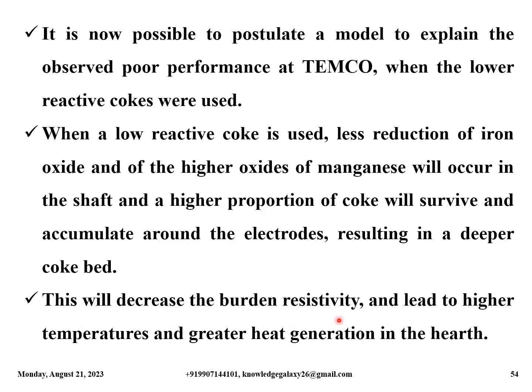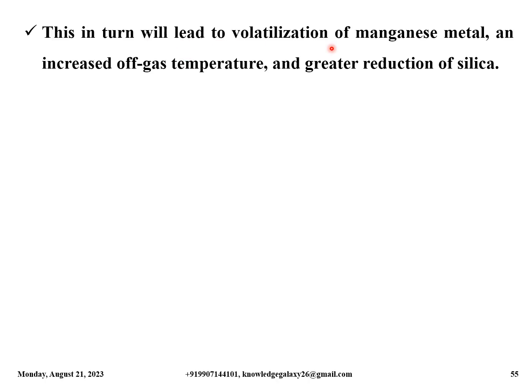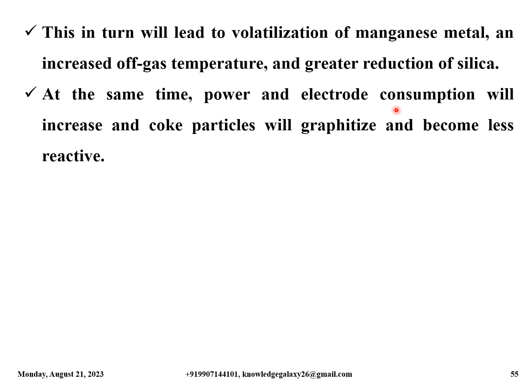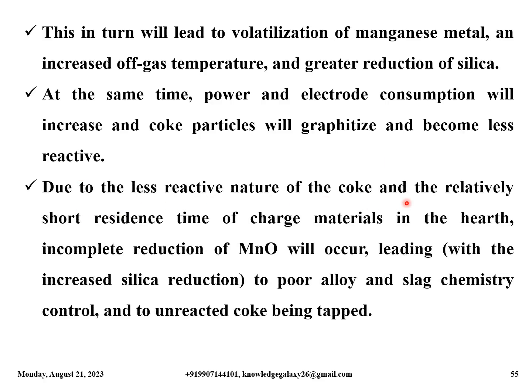This will decrease the burden resistivity and lead to higher temperatures and greater heat generation in the hearth. This in turn will lead to volatilization of manganese metal and increased off-gas temperature and greater reduction of silica. At the same time, power and electrode consumption will increase and coke particles will graphitize and become less reactive. Due to the less reactive nature of the coke and the relatively short residence time of charged materials in the hearth, incomplete reduction of MnO will occur, leading with the increased silica reduction to poor alloy and slag chemistry control and to unreacted coke being tapped.